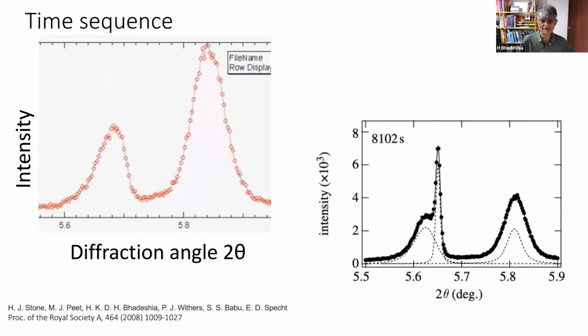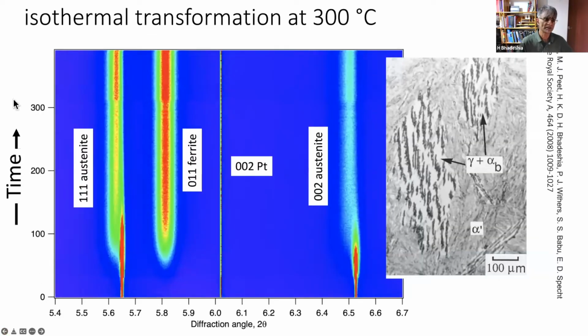So presenting this data slightly differently, time is progressing along here, and this is the austenite before it transforms. As soon as it starts transforming, you develop these two lattice parameters of austenite. And the reason for this is that the carbon partitioned from the bainite enriches the regions around the bainite, but not away from it. So you end up with two different lattice parameters. But this only happens after transformation.